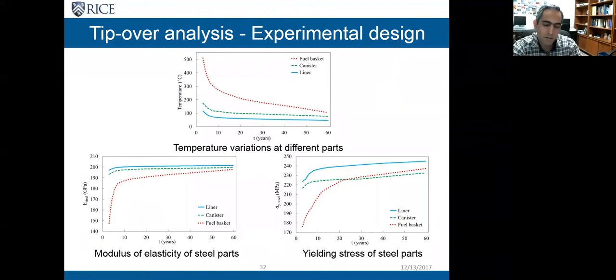Since we considered the age of the cask as a parameter, we needed to update some material properties associated to that. As time passes, the temperature at different parts of the cask go down, and this plot shows how the temperature goes down at different parts of the cask, like the fuel basket, the canister, and the liner. And corresponding to that, the material behavior of these parts, which are made of steel, are affected. These two figures show how the modulus of elasticity and the yielding stress of these parts change in time. If you look at the modulus of elasticity of steel, you see that the main changes happen during the first 10 years of service, which I will talk about more later.